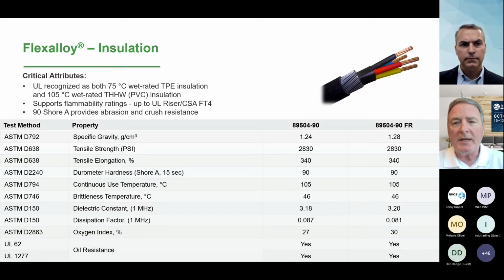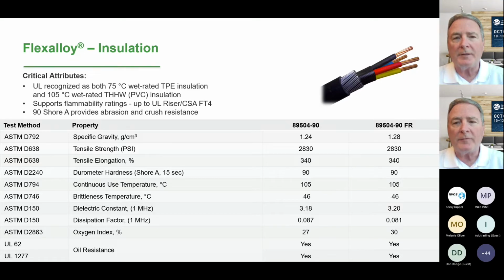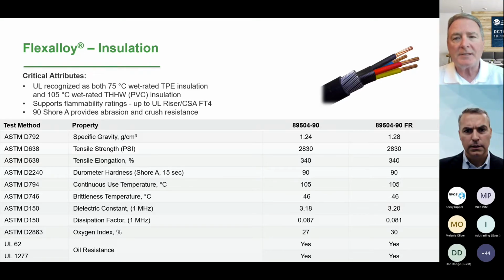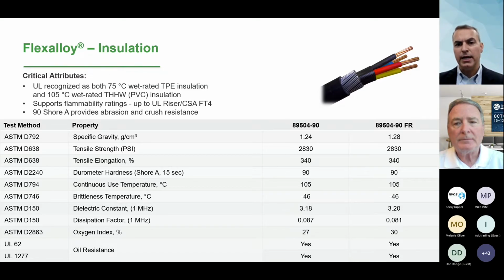Is the 89504 both used as insulations and jackets? We have seen instances where people have used this as a jacket. There's nothing to contraindicate it other than it's not UL listed for 720 hour as a jacket, so they would need to do their own testing for UV, whereas many of the other jacket compounds that I spelled out are UL recognized, I should have said, recognized for 720 hour UV. But there's no inherent reason why this would not be a good jacket choice.